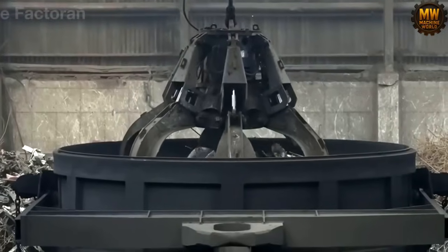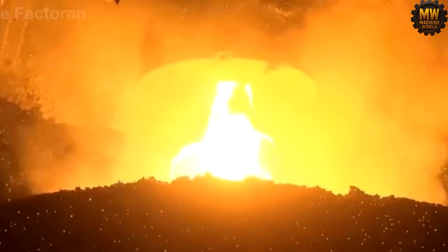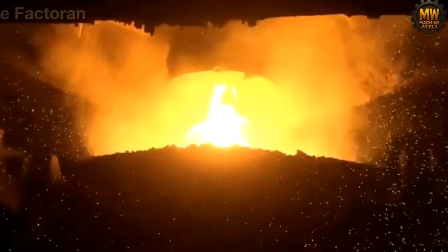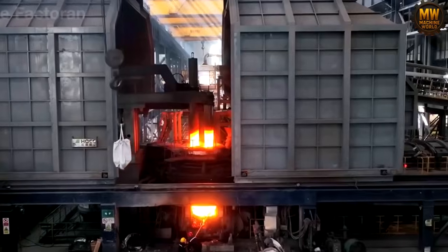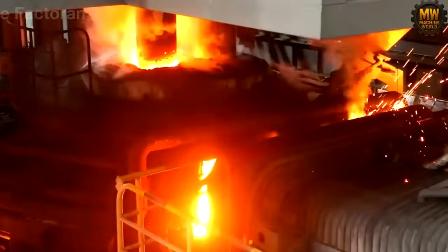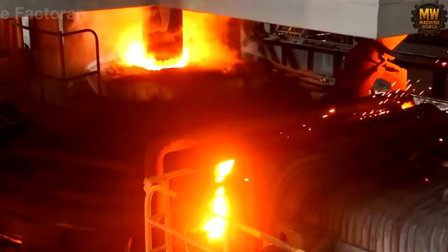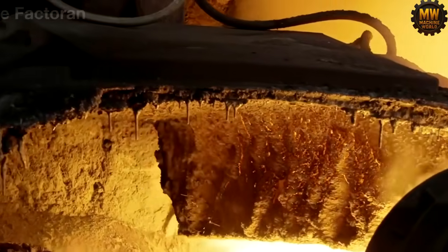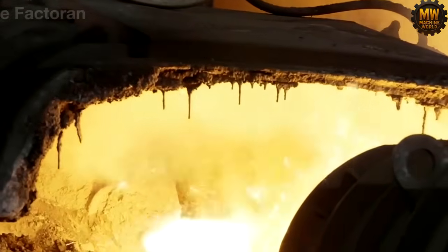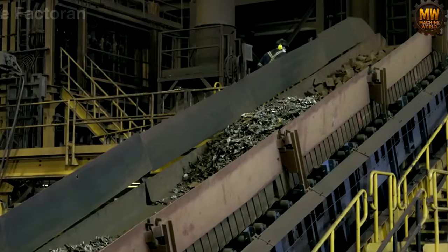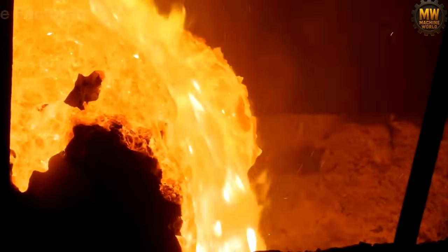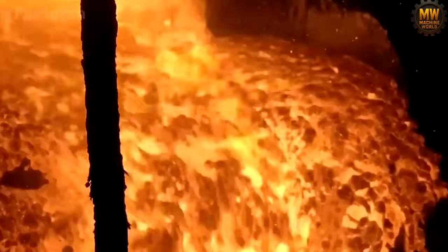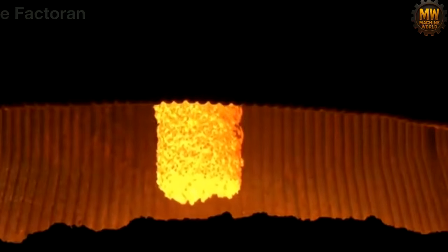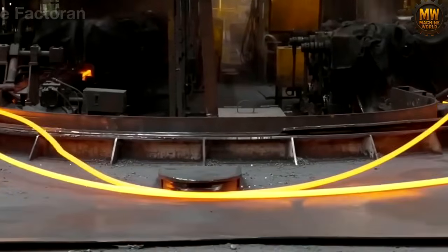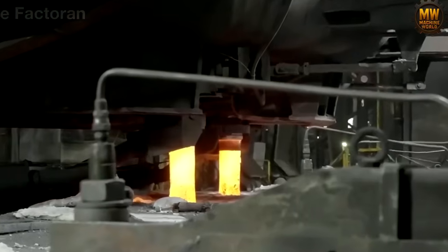Deep inside the vessel, thermal sensors and probes quietly monitor this chaotic environment, confirming the exact molecular recipe without interrupting the violent flow. Zero structural memory. Absolute chemical purity. The chaotic debris is gone, and a completely purified, red-hot mass of homogeneous metal violently surges toward the exit, ready to burst from the furnace. But molten steel does not stay in the furnace for a single second. It pours out as a boiling river to immediately take on a new form.